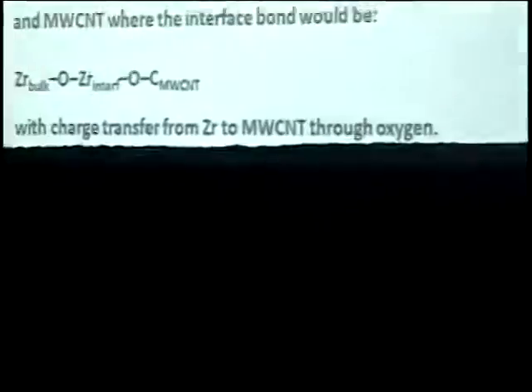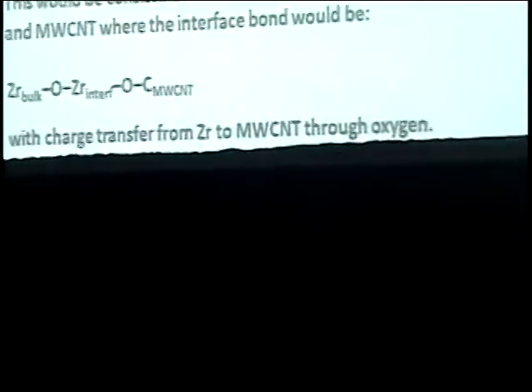With respect to the bulk, this would indicate that when we have small particles bonded to carbon, there's been electron transfer away from the zirconia. And so that's how we come to this charge transfer conclusion, with charge transfer from zirconia to the carbon nanotubes through the oxygen. Now, I'm going to repeat that argument, but not in this detail, as we go to these